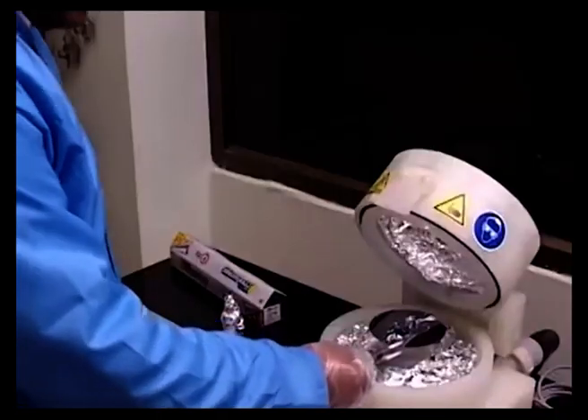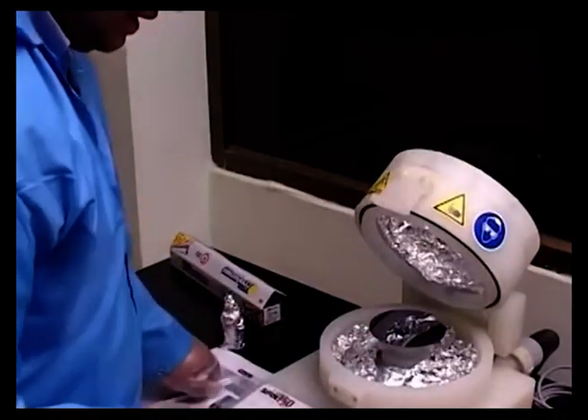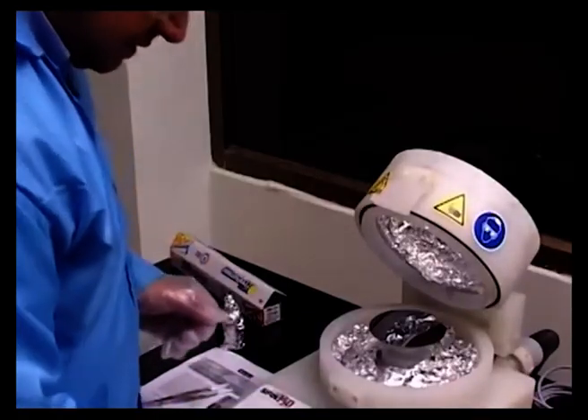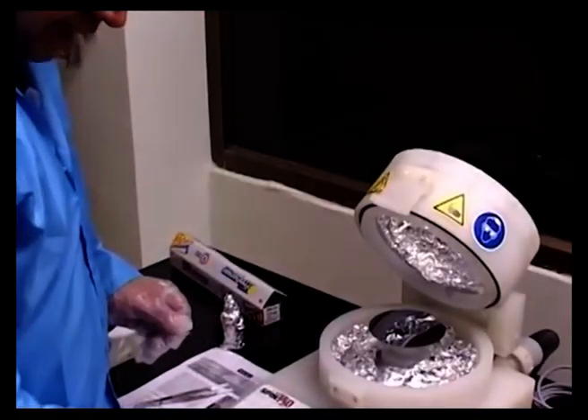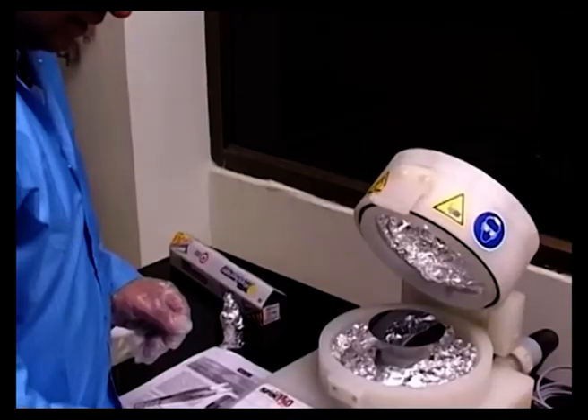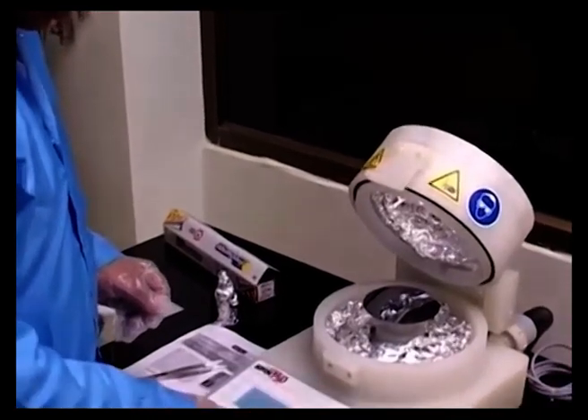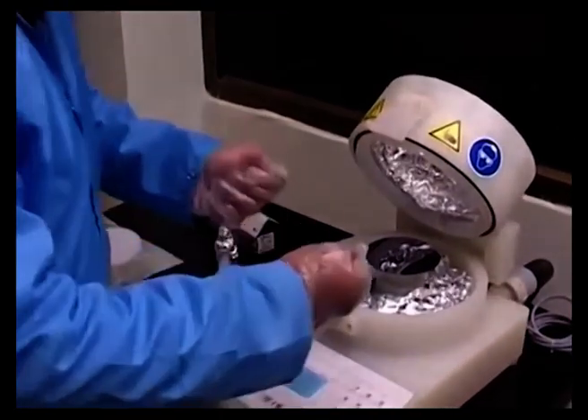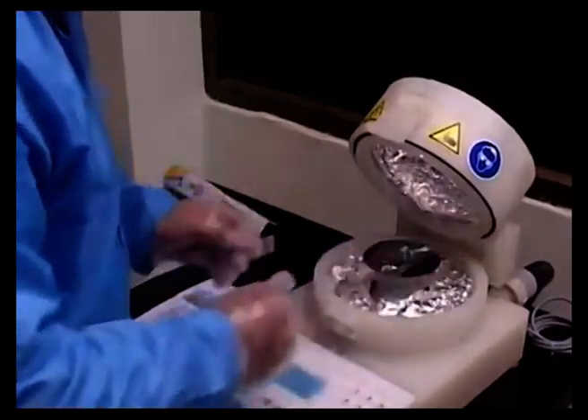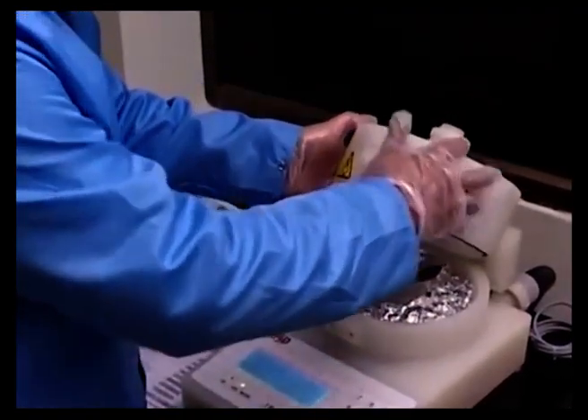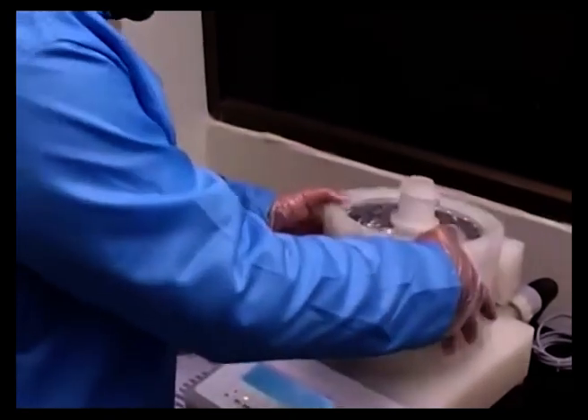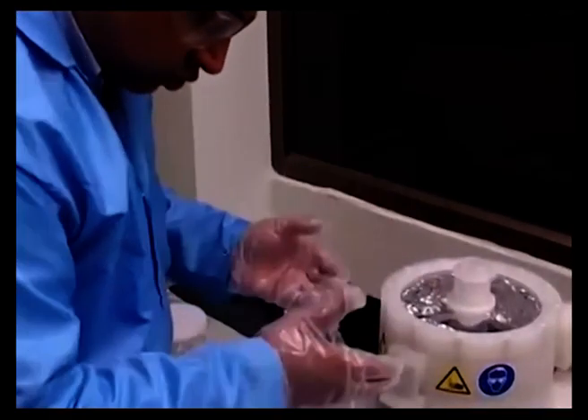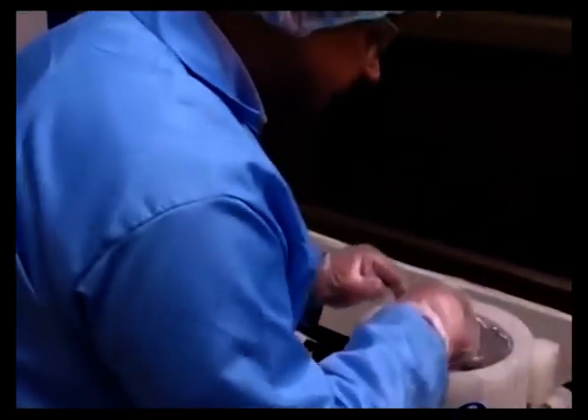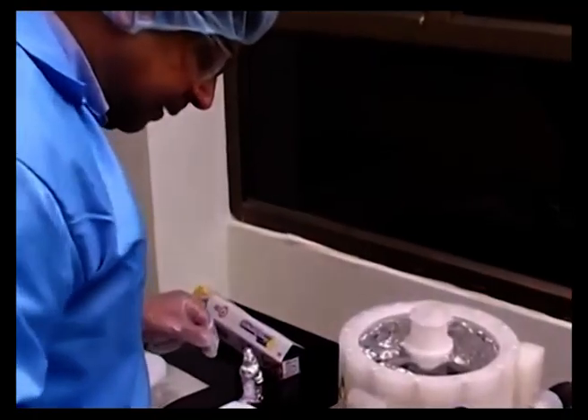So we have now placed the wafer, and what we need to do now is turn on the vacuum here. The light comes on, as you can see here. This is in the on mode. The vacuum pulls the wafer so that it sits onto the spin table, and then we have to see whether the wafer is centered. The way to do it is to close the lid of the spin coater and turn the RPM on so that the system starts rotating, and see from this top transparent area whether there is any wobbling of the wafer.